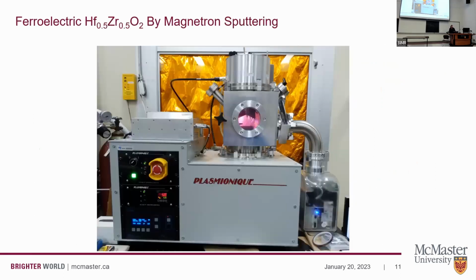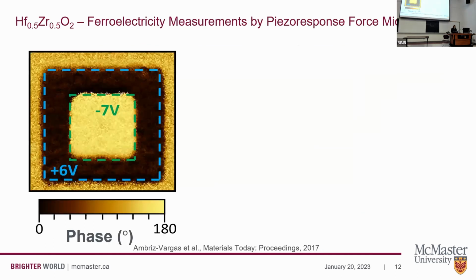So we synthesized this ferroelectric hafnium zirconium oxide using magnetron sputtering. This is a deposition technique that is highly industry favored, as it provides a good stoichiometry control, a good layer homogeneity, and also a good reproducibility. We started by fabricating hafnium zirconium oxide films with a 50-50 content. And the first step was to verify whether or not they displayed some ferroelectricity characteristics.